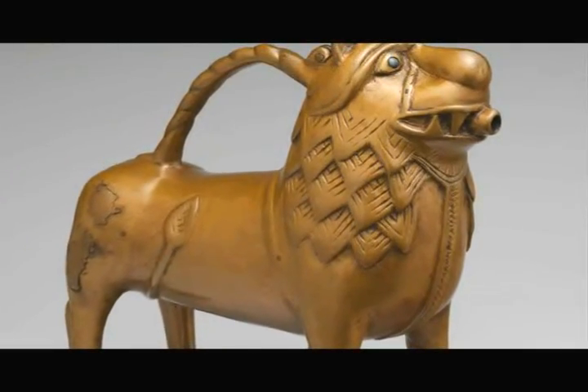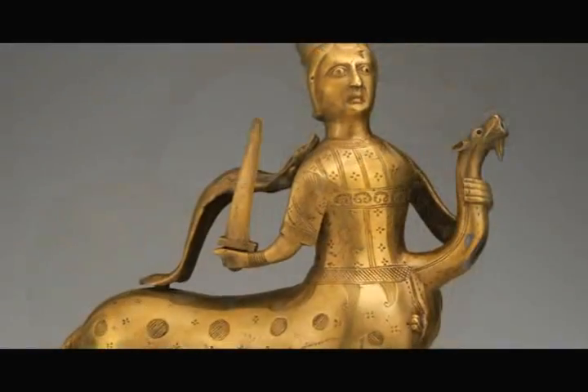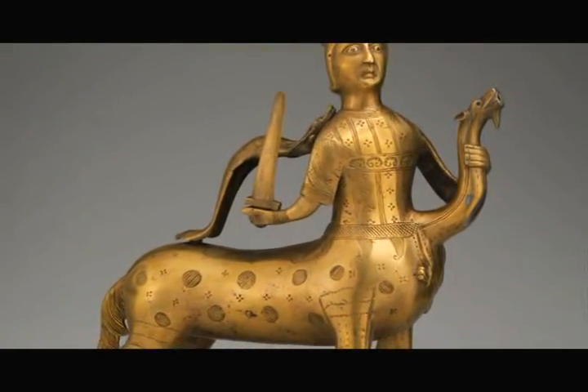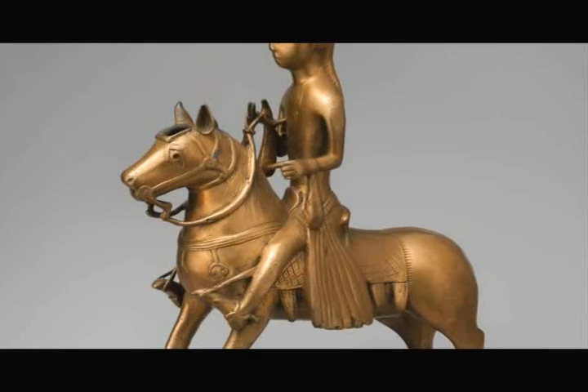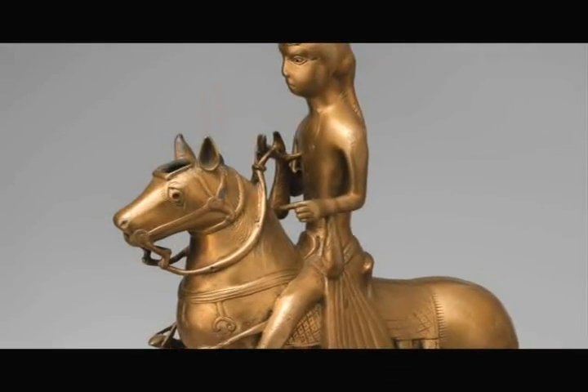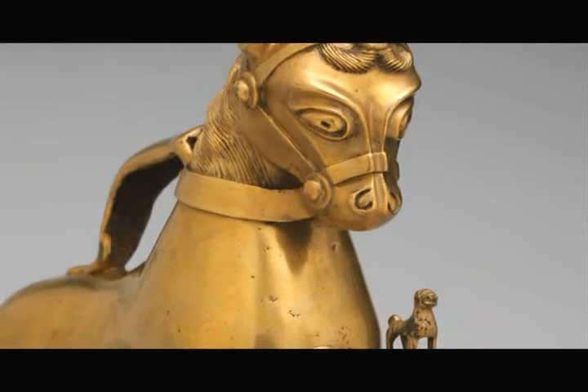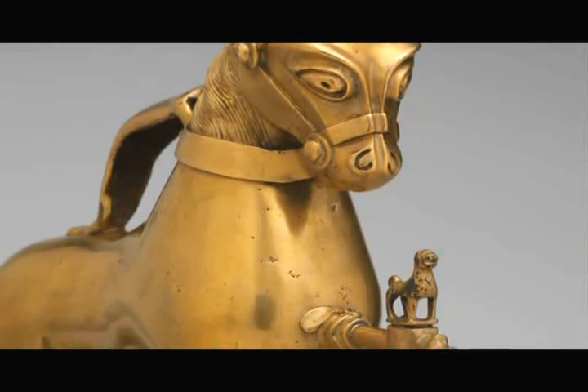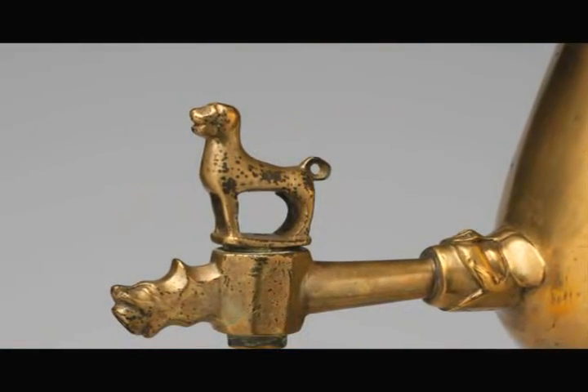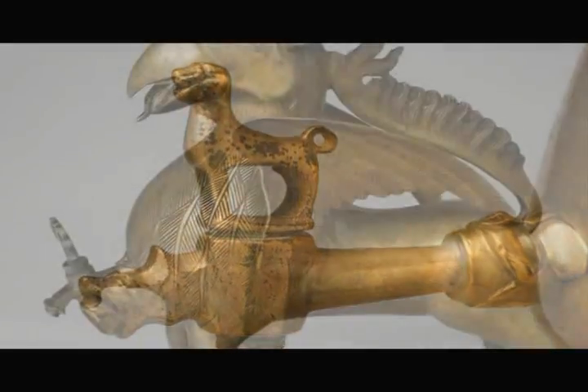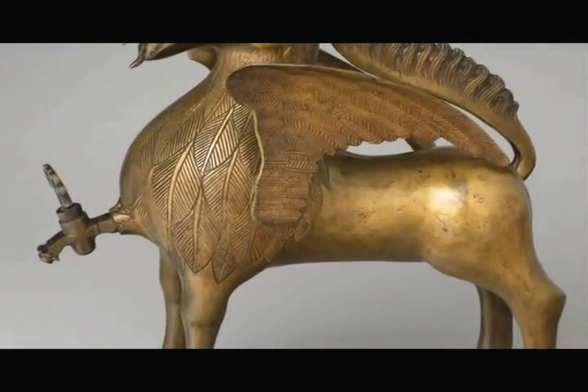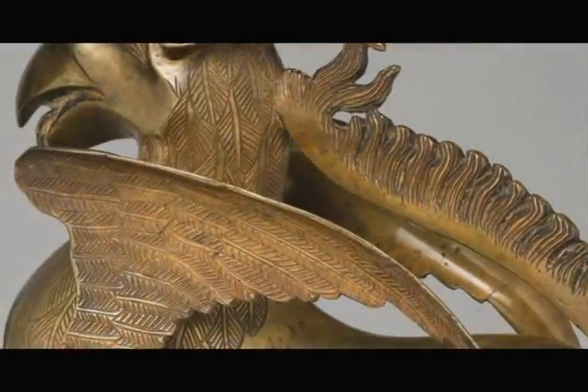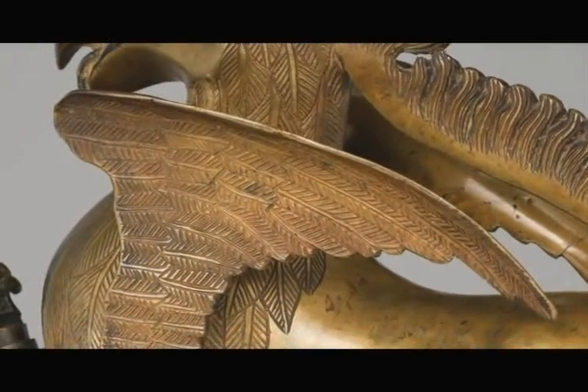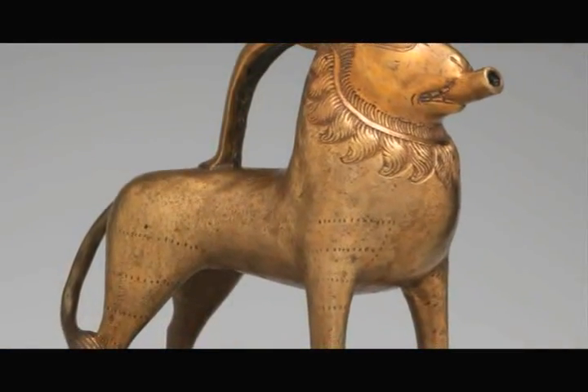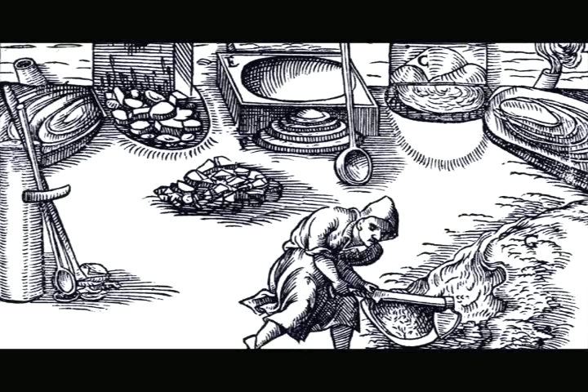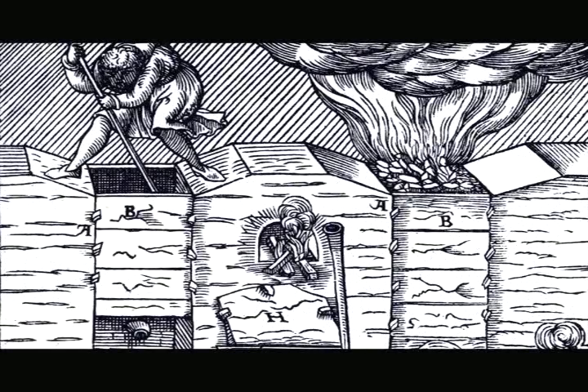The predominant metal used for casting aquamanila and other medieval objects was a copper alloy, referred to as latten, containing zinc as the principal alloying element, with tin and lead present at levels greater than 1%. The raw materials making up the alloy were readily available to the workshops in Lower Saxony, northern Germany, and Nuremberg, which produced aquamanila. Raw copper was supplied to the metalworker from the mining sites. The zinc sources were roasted calamine, either smithsonite, a zinc carbonate, or hemimorphite, a zinc silicate, and tutty, zinc oxide, derived as the byproduct from the smelting of lead ores.